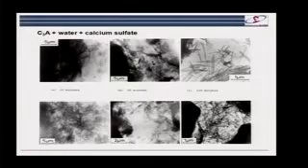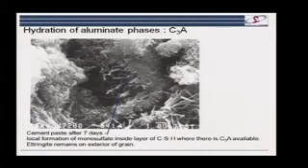No way. In fact, what happens is the sulfate ions absorb on the surface of the C3A and slow the reaction down. But this is how ettringite forms, reacting with C3A. So that's what I've just said here. The reaction of C3A is not blocked directly by ettringite, but is controlled by the absorption of sulfate ions. We can find that later on we form this monosulfate phase, and this is where it kind of gets